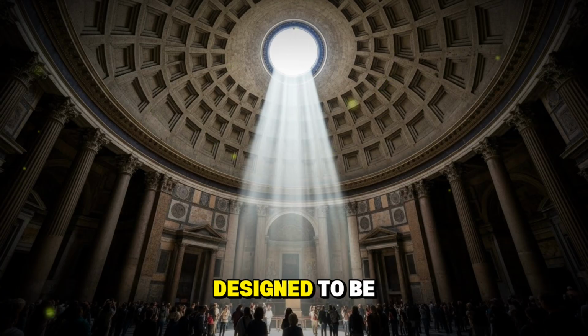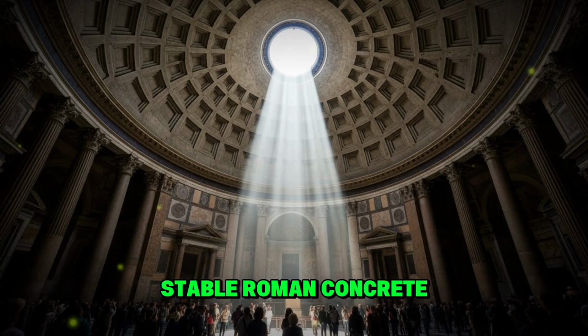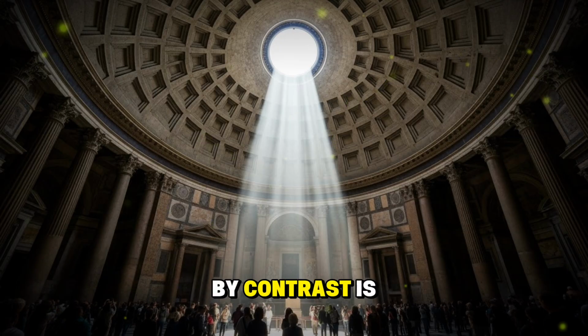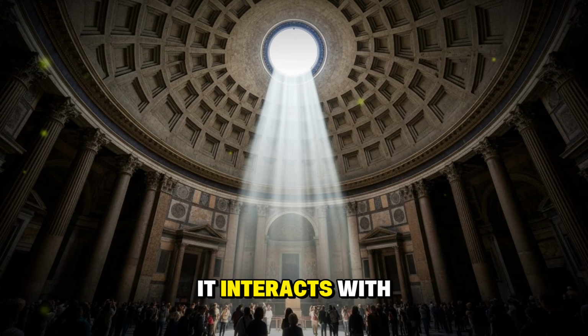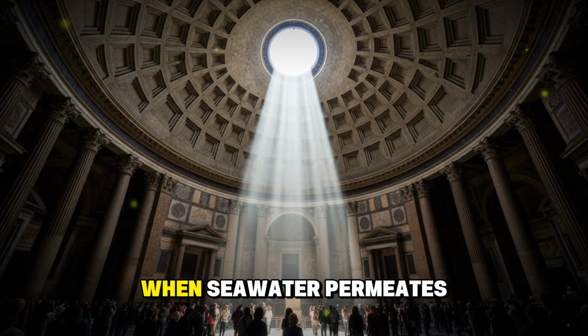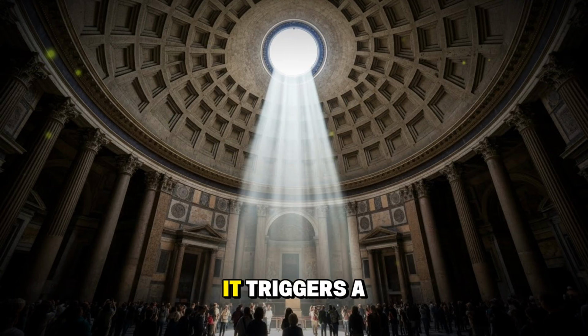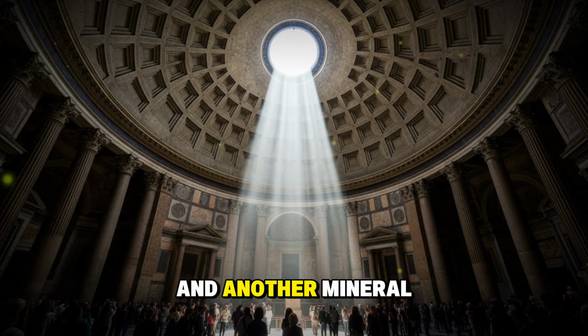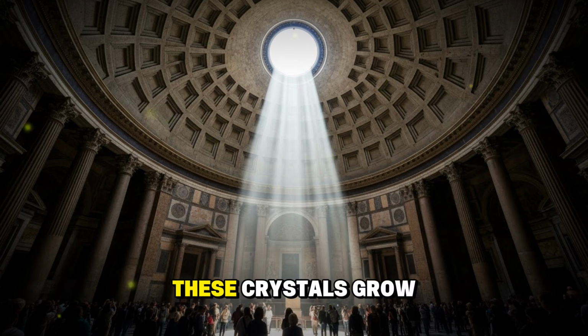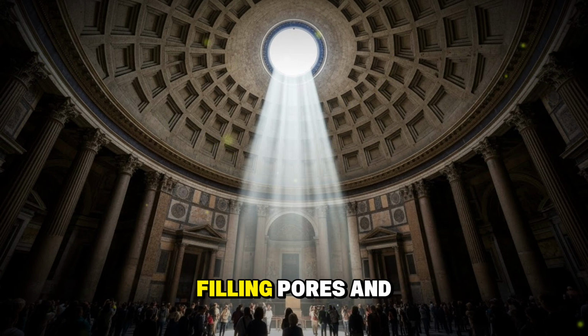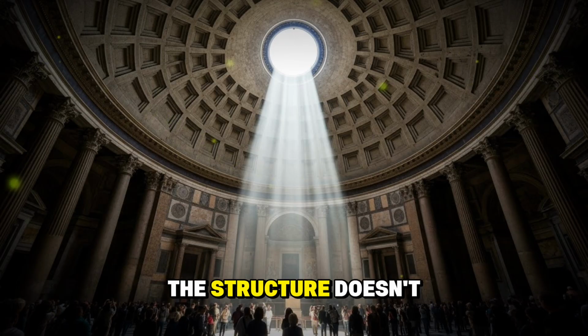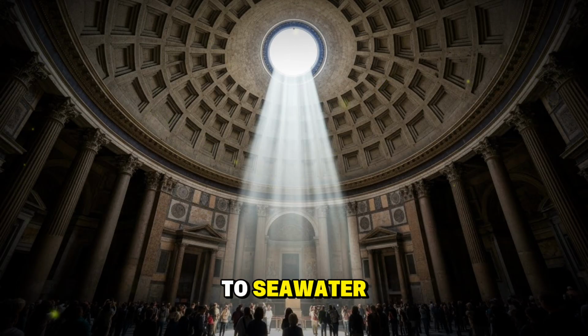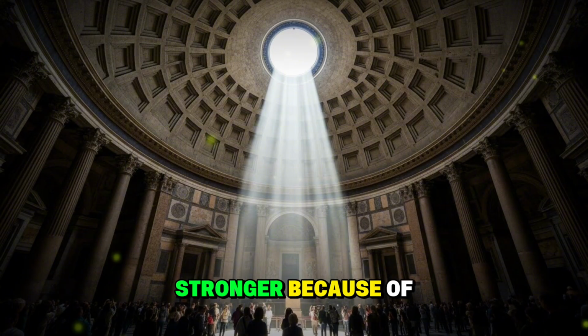Modern concrete is designed to be inert, unchanging, stable. Roman concrete, by contrast, is chemically active. It interacts with its environment, and in that interaction lies its strength. When seawater permeates through Roman concrete, it triggers a chemical reaction. The volcanic ash in the concrete reacts with the salt water to form aluminum tobermorite and another mineral called phillipsite. These crystals grow within the concrete matrix, filling pores and strengthening the material. The structure doesn't just survive exposure to seawater, it actually becomes stronger because of it.